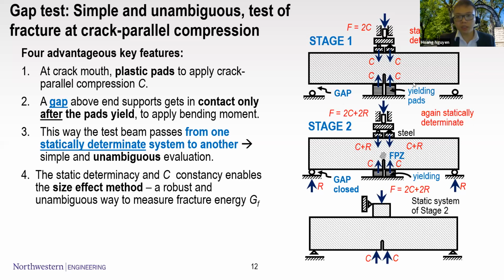You have a single edge notch specimen subjected to something like 4-point bending, but it's not quite right, because in the 4-point bending test, you have 3 equal span lengths. In this one, the load is applied at 2 points at a separated distance. At the beginning, the specimen sits on a yielding pad, made of a plastic material, and the requirement I will mention later. After the load is applied, the pad will deform elastically and then plastically, but the specimen will not be subjected to any bending moment, because there is a gap here.